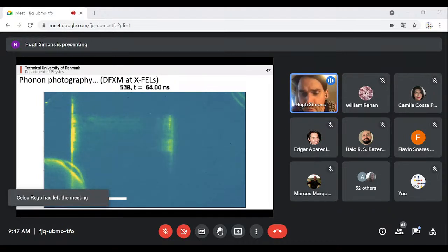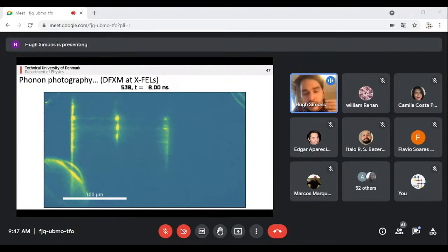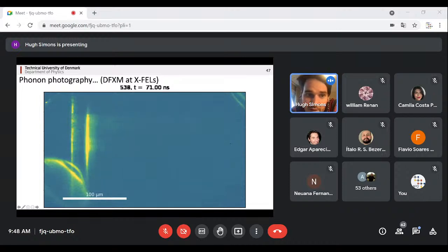And what we did in our experiment, this is very new data, it's only a month or two old, is we took a single crystal of diamond and repeatedly hit the diamond with light pulses to create a repeating shock wave, or essentially a single acoustic phonon propagating through the material. And then we're actually able to image this acoustic phonon from the strain fields that they're associated with. So that's exactly what you're seeing here, an acoustic phonon being propagated through the material. It splits into longitudinal and transverse components, which have slightly different velocities, which is what you're seeing here. And then you can see they bounce back from the back of the sample to the start again.